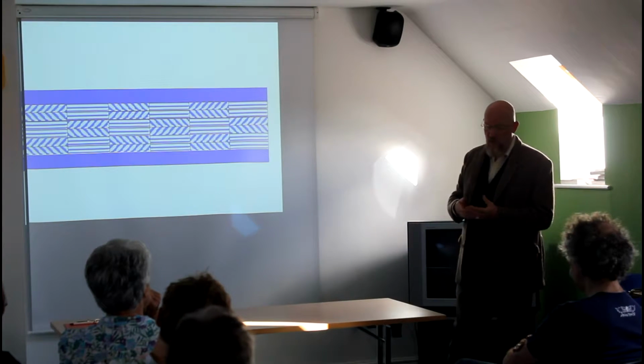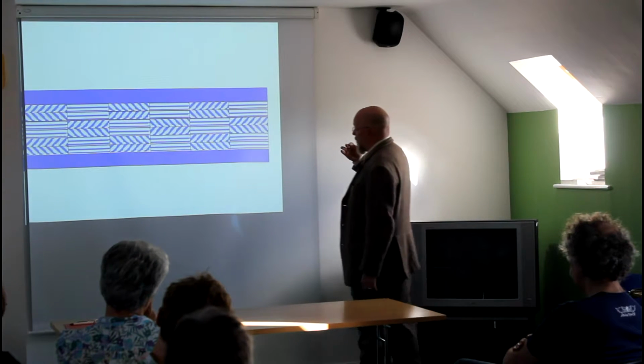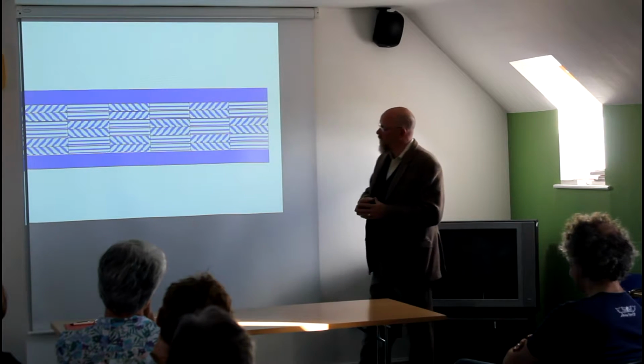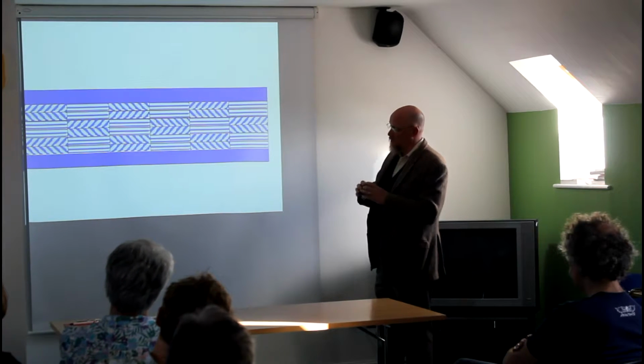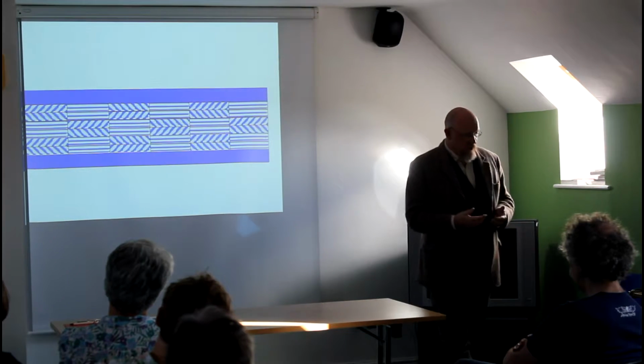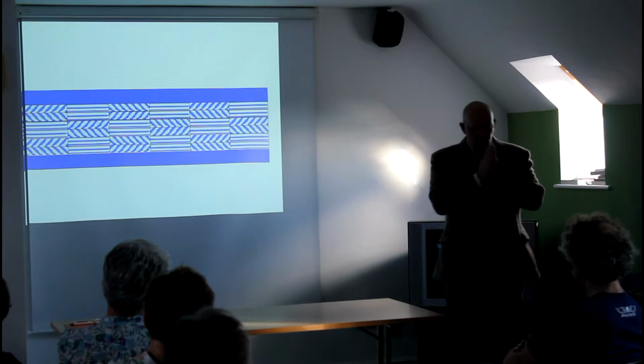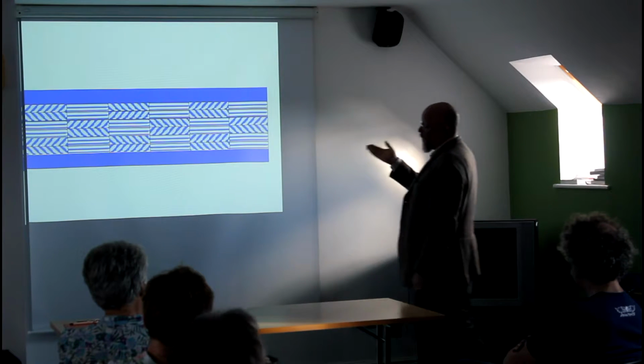So you're not looking at a sword that's made out of one piece of iron or steel. This is made out of hundreds of individual pieces of iron that are put together to form the core and then edged in steel to give you a cutting edge. And it's a technology that's very advanced, and it's similar to the Japanese style swords that we see in lots of samurai films and things like that. But the Japanese technology goes into having edge strength, whereas this will give you all-round strength.